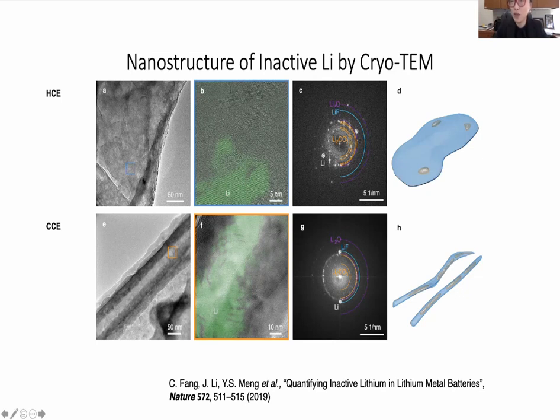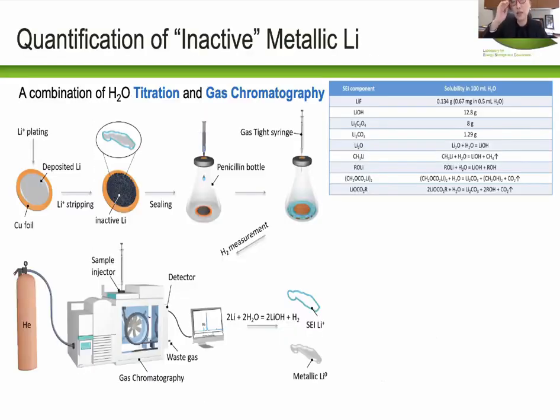So when you look at the cryo imaging, you see this is a conventional electrolyte. Really, the morphology of the lithium grown is whiskers, right? If you change the electrolyte to ether-based electrolyte, they really are large granular crystals. And then the SEI, you see in the whisker shape, there's a lot of this metallic lithium that is encapsulated inside the SEI, right? So from our observations, we really do not see any component difference in the SEI between the new electrolyte and the old electrolyte. So then Chen, my student, now an assistant professor at Michigan State, we said, let's go and quantify how much metallic lithium is actually left there.